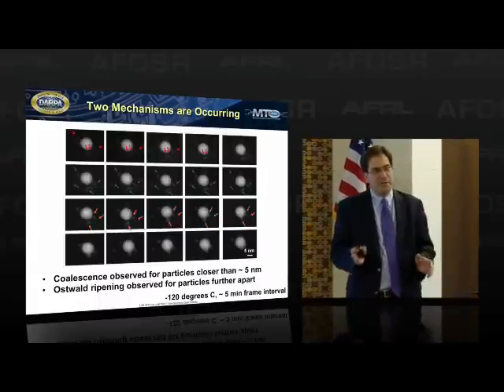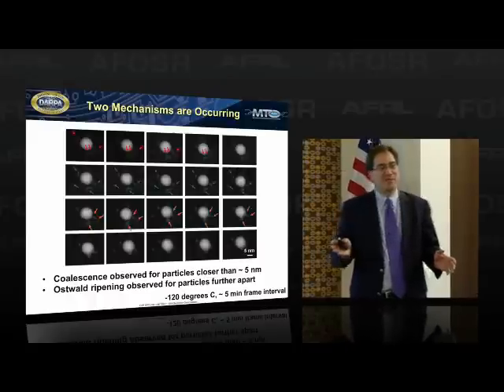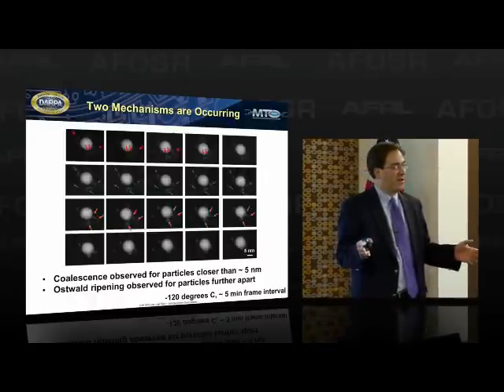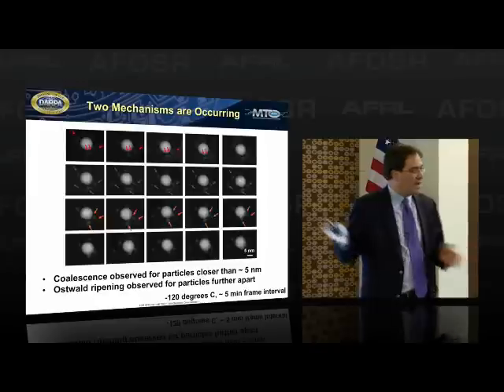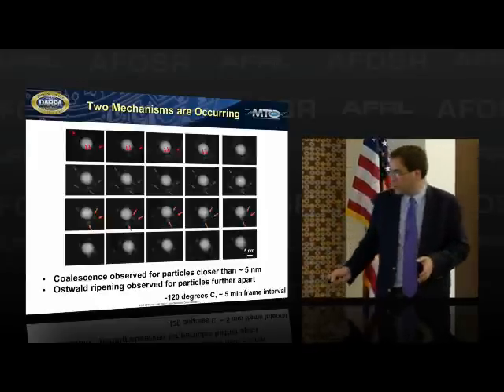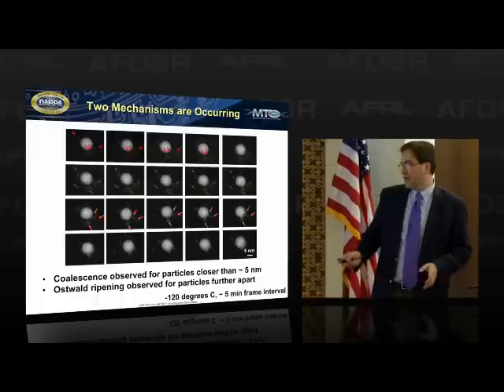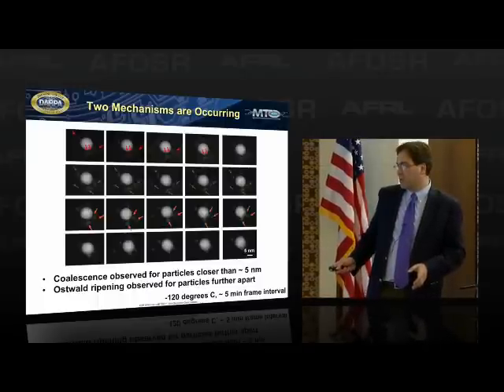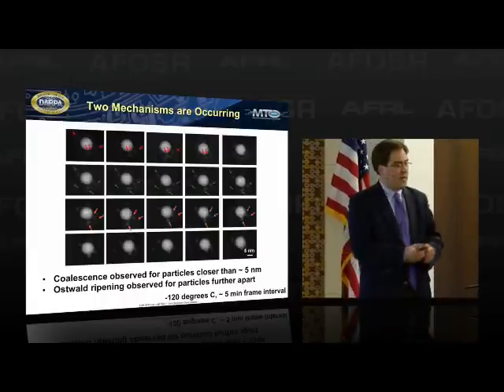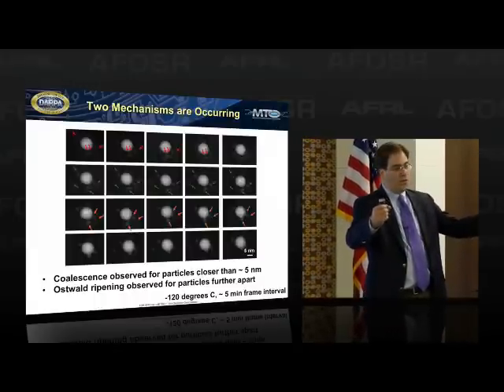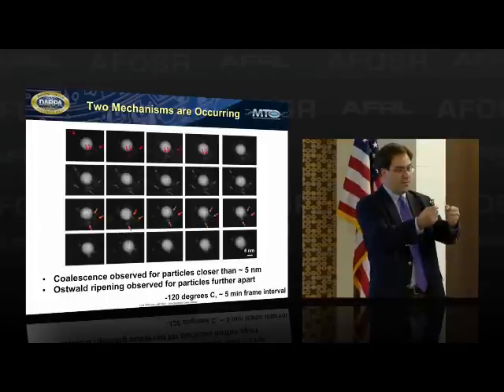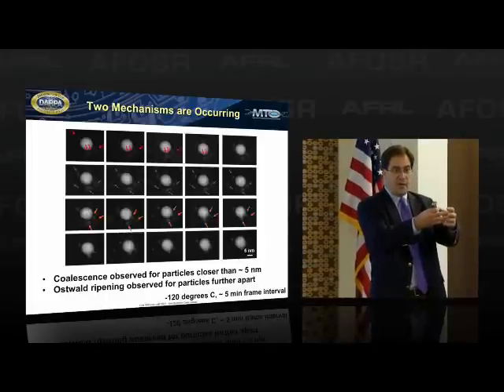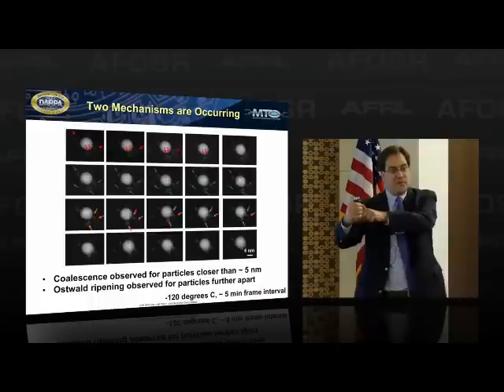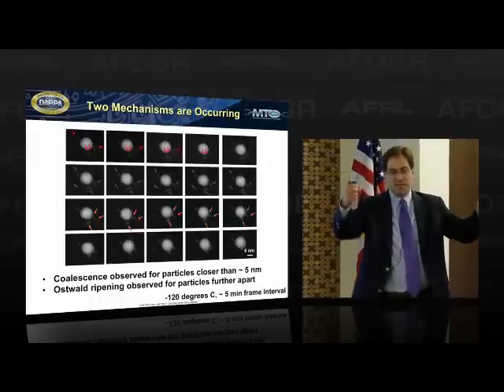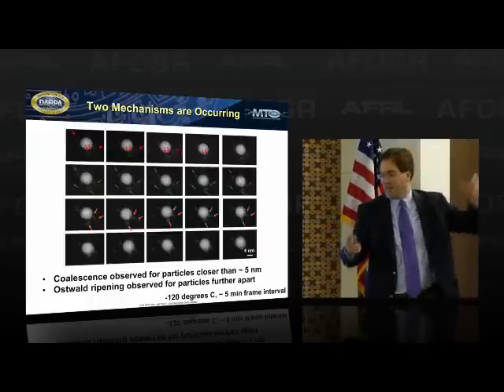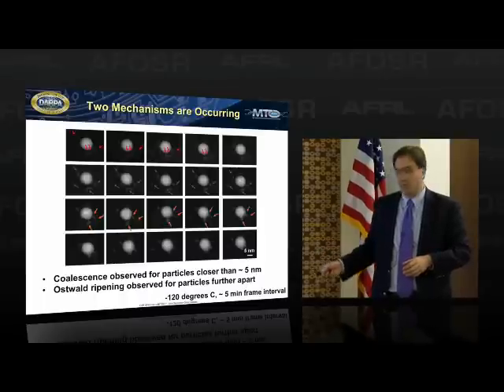But what's really neat about this is it gives you a way. I teach general chemistry, and we always talk about Ostwald ripening. Nobody ever shows you that. Well, now you can actually watch it. And in fact, you can differentiate it from coalescence. It turns out that coalescence is observed for particles closer than 5 nanometers, whereas you get ripening if they're further away. By that I mean, in one case, particles are fusing with one another, and they're kind of consuming those that way. In the other case, they're remaining fixed, and atoms from this are going to atoms from this, and this guy's slowly dissolving while this guy's growing. And you can tease out from these types of experiments that the critical distance is 5 nanometers.